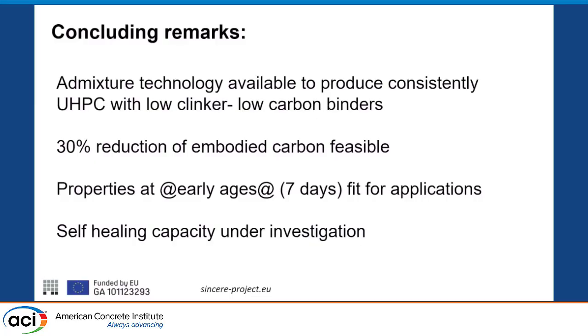Properly, I would say this is a strange sentence, because 7 days could not really be early age, but it's still something that you do not compare to the 28 or 90 days, and it's related to the productivity and fit for the applications that we wanted. And also we are investigating the self-healing capacity of these UHPC-like materials in order to keep the long-term durability performance that we wanted for our application.